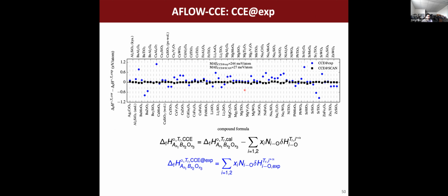So CCE, if we just look at the raw corrections, we can actually extract out a rough value of what the formation enthalpy should be. And you can see here, the rough values have an error associated with them. Let's say we don't have our calculations from which to correct our enthalpies of formation, we can still get out what's called a rough estimate of what the formation enthalpy is. Now, it has very large errors here, but the idea is that we can actually look at what the formation enthalpy could be, even if we don't have a calculation from which to subtract it off. So the ideal scenario is that we have a DFT calculation and we have a correction for it. But even without that, we can still use CCE to get a correction just based on experiment.